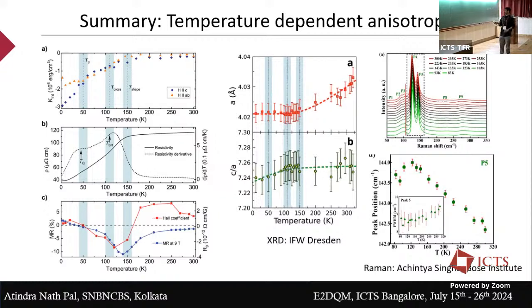What do you observe from our data? You can actually fit an anharmonic model to that. But near the spin reorientation transition, till 77 Kelvin we could do, and you can see there is a clear drop of this signal. It doesn't follow the anharmonic model, just pure temperature dependent model. So that means the spin phonon coupling definitely is changing here, and that probably means lattice and magnetism are mixed near this 120 Kelvin spin reorientation transition.